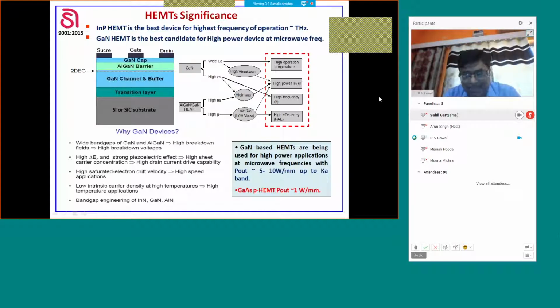And just for comparison, the gallium nitride HEMTs give power density of the order of 5 to 10 watt per mm up to Ka-band, whereas in gallium arsenide pHEMT or indium phosphide pHEMT, the power density is restricted to 1 watt per mm. So when we are talking of systems of very high power density, one has to go to gallium nitride based systems. And since the density is very high, we get a lot of advantages in size and weight considerations, which are very important for airborne applications.